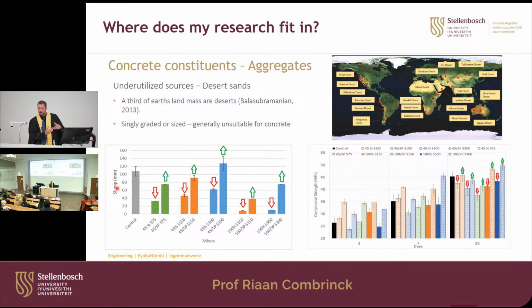So the slump is an indication of the fresh and workability properties of your concrete. As you can see, the red arrow shows that as you add desert sand, your slump decreases, so it's more difficult to work with the concrete. But as a remedy, if you look at the green arrows, as you add just a small amount of superplasticizer, you can get that slump up again to close to the control. So with some specific tweaks, you can still use the desert sand.